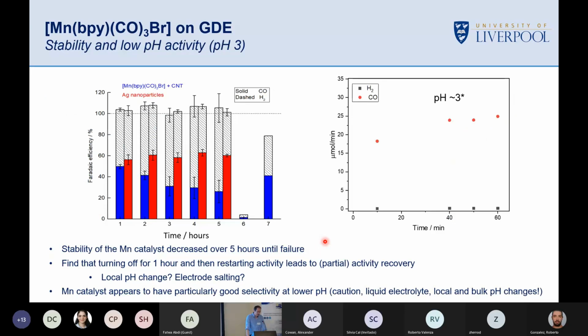So what happens now at lower pH? Well, we can change the electrolyte out. We can put in a pH 3 buffer, and we actually get improved CO Faradaic efficiency, so that's really good. We thought we might. There's a huge caveat with that: this is only lightly buffered. We know the local pH is much, much higher. We can run the experiment for a very short time before we're having to adjust the pH. So it's interesting, and it gives us a clue it might work.